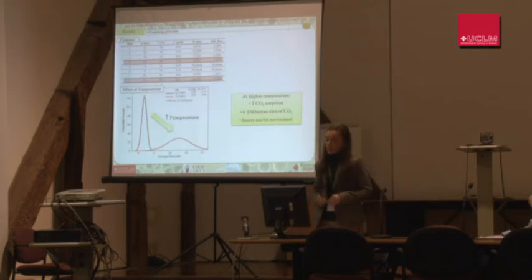Nevertheless, when we increase temperature, we observe that bigger cells were obtained and they weren't so homogeneously distributed. This is because the carbon dioxide sorption decreases when temperature increases, and consequently fewer nuclei are formed. For this reason, the cells that are formed grow very, very quickly, but they grow in an asymmetrical way.